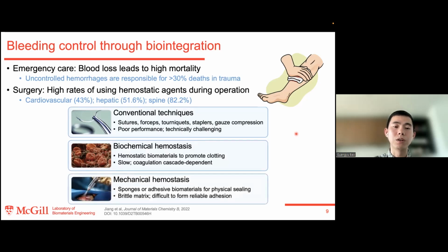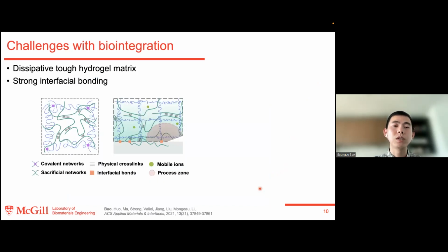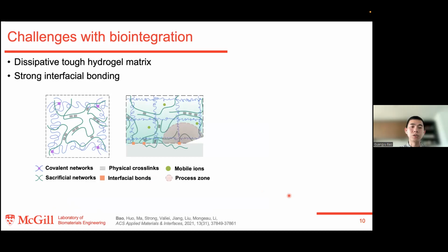The other strategy is mechanical hemostasis, where the biomaterials are used to physically seal the bleeding site. These materials should robustly stay at the wounds through integration with the tissue. This strategy does not rely on the coagulation cascade, so potentially it is suitable for a broader range of scenarios. But most existing sealants are mechanically brittle and difficult to adhere to the bleeding site. Recently, people have found that the key to achieving tough adhesion between hydrogel and tissue is to have an adhesive interface and a tough adhesive matrix.